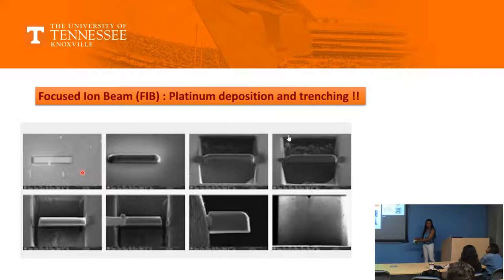So that's what you're doing step by step. But we are operating at a micron level, so you would be very careful. It's a procedure that you do with the needles. Now here you deposit the platinum and you keep the thickness of this platinum enough so that it protects your material. I would be helping you with the exact numbers during the lab.